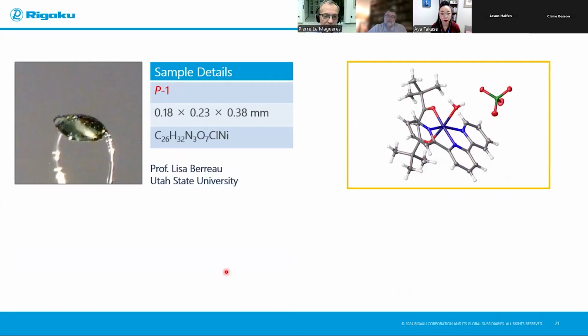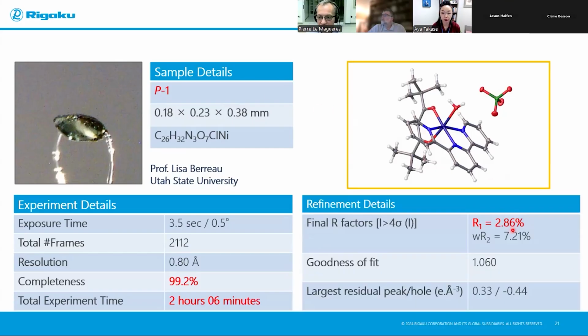Another organometallic compound, or coordination compound of nickel, provided to us by Professor Lisa Berreau from Utah State University. You see the crystal structure on the right-hand side. Beautiful crystal again, larger crystal though, right? But low symmetry, and data collection completed in just 2 hours. 99.2% completeness, 0.8 angstrom. Beautiful structure with an R1 at less than 3%. So I just showed you a few tough examples, but you see that as soon as you have a good-ish crystal, within a couple of hours, maybe a handful of hours, you will get your crystal structure.